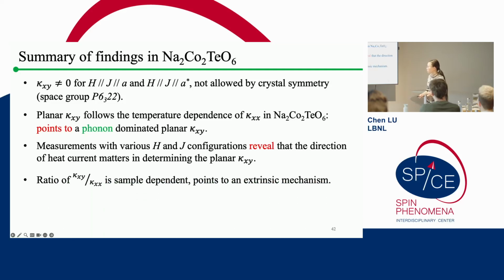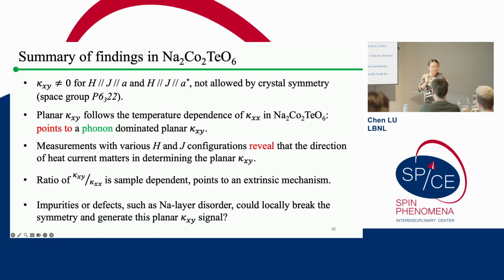The next finding is that this planar thermal Hall effect is highly sample dependent, which points to some extrinsic mechanism. The remaining question to be answered is, what is the mechanism behind that? I mentioned that symmetry-wise, there is some kind of dilemma that needs to be answered. One thing we know, particularly regarding this material, is that it is a layered material, and one of the sodium layers, which is sandwiched between the Kitaev honeycomb layers, is in a highly disordered state. This means you can have some local disorder, which can probably locally break the symmetry. But then the question is, can locally broken symmetry give you a global non-zero planar thermal Hall effect? We don't know yet, and we need some help from the theorists.